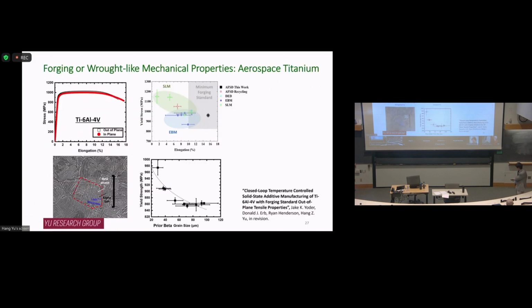And also we have demonstrated something similar in Ti-64. This curve is as-printed material, because with Ti-64 you don't have to do aging to get precipitates. It's essentially a two-phase alloy. And we show that you can get similar mechanical properties in plane and also out of plane. That's pretty remarkable, and it also falls into this regime of forging standard. Also, we tried to understand how the strength depends on the prior beta grain size. Again, I want to give you the message that this process gives you a convenient pathway to achieve excellent mechanical properties compared to the fusion-based additive process.